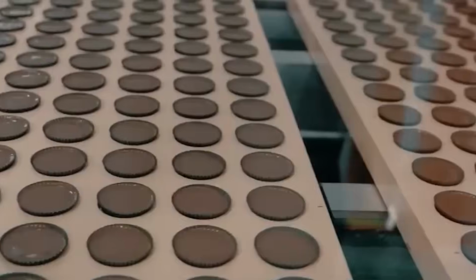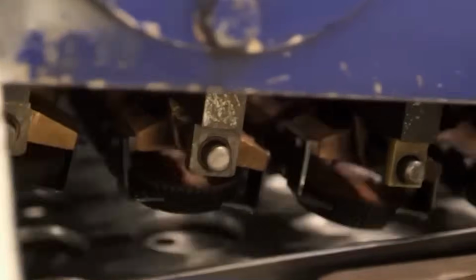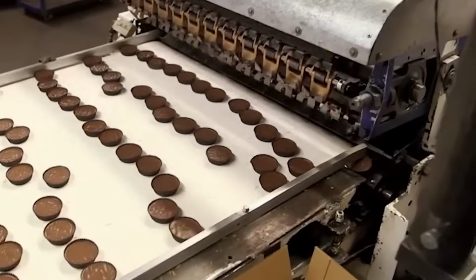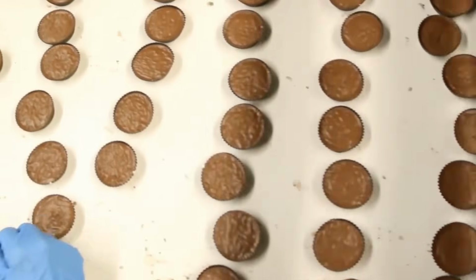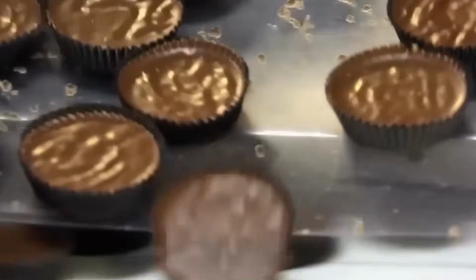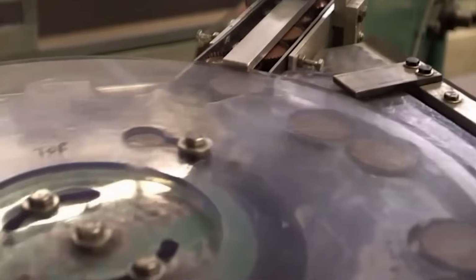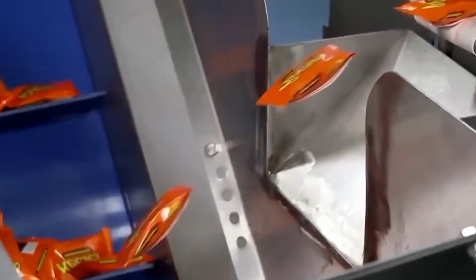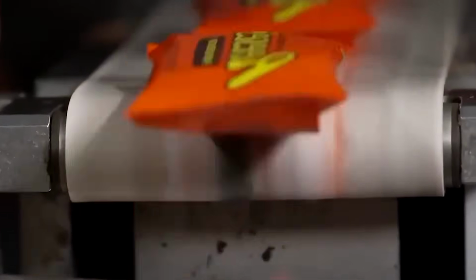The filled cups then pass through an extended cooling tunnel where they spend several minutes gradually chilling back down to around 45 degrees Fahrenheit. This staged cooling prevents the chocolate from blooming, a condition where cocoa butter rises to the surface and creates an unsightly white film. Instead, the cooling process locks in that deep, shiny chocolate sheen. Once fully cooled, the cups are ready for packaging.